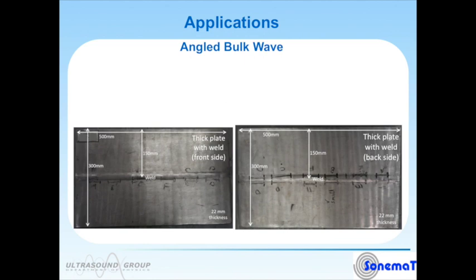It's long been hypothesized that an SH angle bulk wave would give high sensitivity. And we believe the paper published in this area is a first demonstration experimentally that taking the best case standard compression wave type inspection, you can't see all the defects in this plate. Using the angled SH bulk wave EMATs, it was possible to inspect this plate from any single side of the weld and find all of the defects. This proved to be impossible using alternative ultrasonic methods.